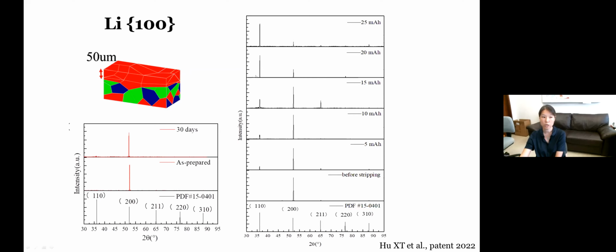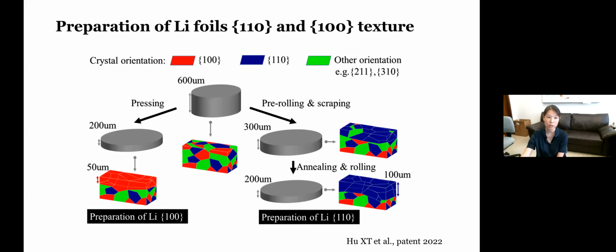With that estimation, the thickness of the surface texturing of lithium 100 is about 50 microns, but that hasn't taken into consideration the X-ray attenuation depth. So if that is taken into consideration, we would have at least 100 microns of lithium 100 on the surface of the lithium foil. Now, as said, the preparation of the lithium 110 is what we hoped for, right? But that takes a bit more effort.